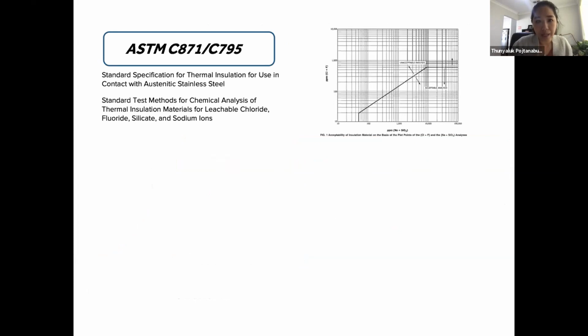So at the moment, there are a few guidelines or acceptance criteria when we select the insulation materials. The first one being the ASTM C871 and C795. These two ASTMs go together. The one basically says how to test the leachable ions of insulation material, and the other one provides a specification for use with the austenitic stainless steel. So we can see in the diagram here, it provides an envelope of where insulation is acceptable in terms of the leachable ion content, and that is a ratio between chloride and fluoride versus the sodium and silicate. So high concentration of sodium and silicate lead to a more inhibitive effect, so that would be within the acceptable range. On the contrary, if the insulation leaches chloride ion to an unacceptable amount, then it would fall out of this envelope.